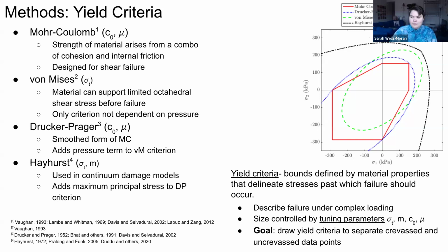So we use 4 yield criteria, and these criteria are based on certain material properties. The size of the criteria is determined by certain tuning parameters, which are in parentheses next to them. These are the cohesion and internal friction for Mohr-Coulomb and Drucker-Prager, and then just the tensile strength for von Mises and Hayhurst. What's really cool, in my opinion, is that these criteria all kind of build off of each other in a way.